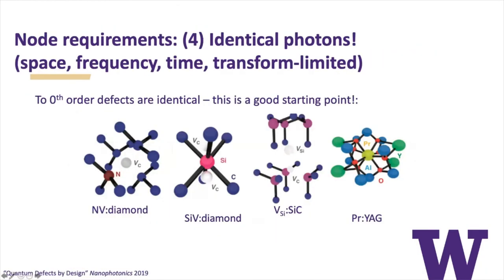And then the final requirement is that you need these defects, if I have two different nitrogen vacancy centers, to emit identical photons. Another way to say that is that their energy structure needs to be identical. And to zeroth order, defects are identical because a nitrogen vacancy center in one part of the diamond should be the same as in another part of the diamond, which should be the same as if someone else looks in their diamond sample. Similar other types of defects that are used for these applications are the silicon vacancy center in diamond. People are looking at single vacancies and divacancies in silicon carbide, and also rare earth doped crystals are also contenders for these applications.